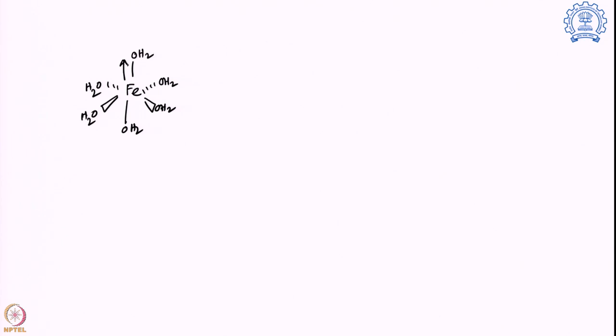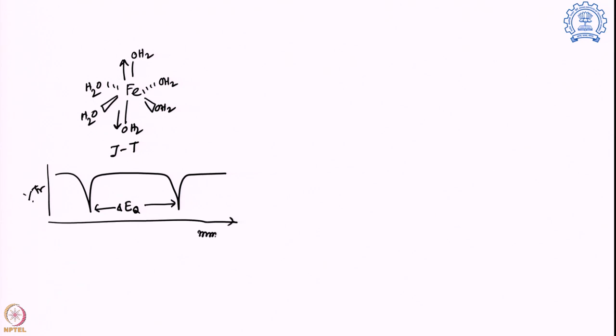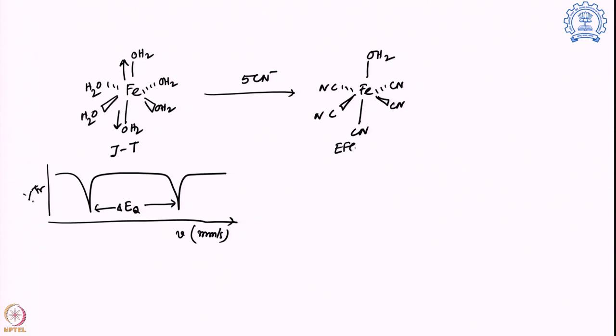So it is going to have a Jahn-Teller distortion. So that is what I am going to see, a huge distribution of delta EQ. Anywhere you are showing a graph, you should show the axis. And then 5 cyanide molecules come and replace it. So over here there is no more electric field gradient from the valence, but the lattice one is still there, and previously JT was there and valence EFG was there.